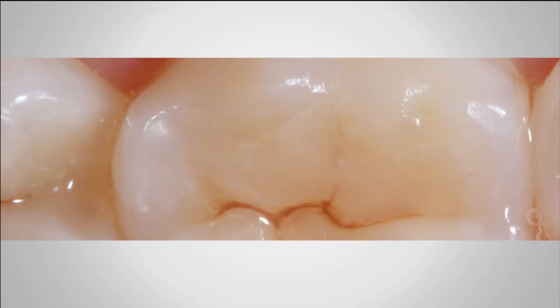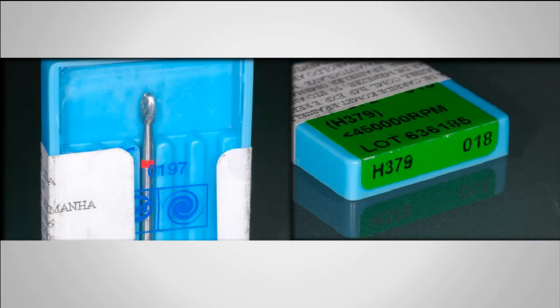Every time your patients say, I feel a little bit with cold, this means I have a problem on the interface. And usually this is created by this excess of adjustment, using too much diamond burr in a high speed. So ideally you should adjust less. Ideally you should use this burr. This is a carbide burr from Brasseler. The reference is H379. And ideally you should use this burr with low speed, not with high speed.